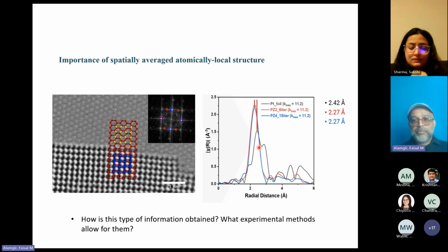So just to put a punctuation on this slide here, this kind of work was done prior to this kind of work in our lab. In other words, we understood already that there was epitaxy going on, because that's the only way we could explain the compression of the platinum-platinum bond distance before we had a visual proof of that. So I'm not saying that one is necessarily better than the other, but they work very well complementarily. Okay, so another flavor of this local information is local in terms of the atomic neighborhood, but spatially averaged.